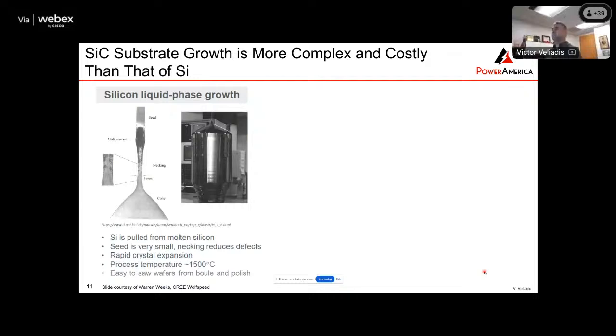So the first thing we want to know is the substrate. You need a substrate to make silicon carbide devices, and I will do the comparison with silicon. If you look at silicon, you need to go to temperatures of 1500 degrees, and then silicon melts, and then it goes through this necking process that minimizes the defects, and you're able to get large boules in a very short time, and then you can slice those easily into wafers and polish them.